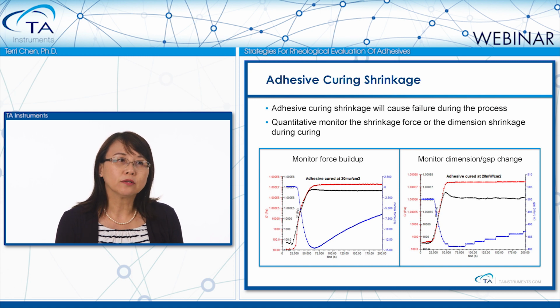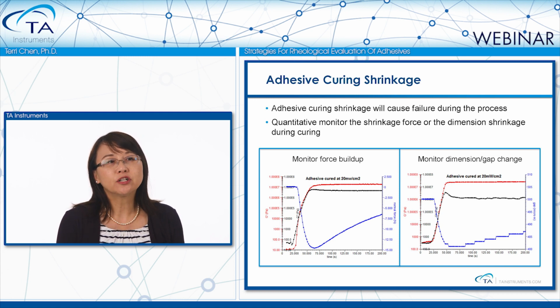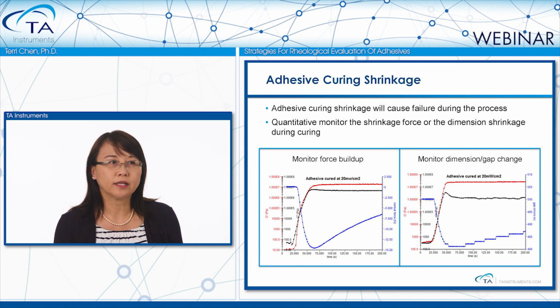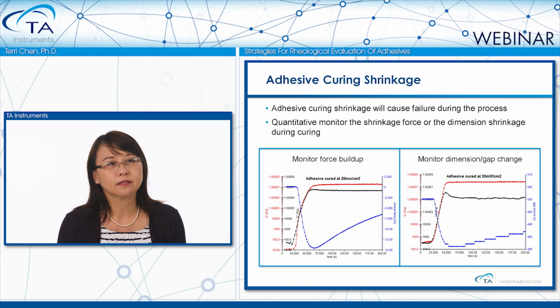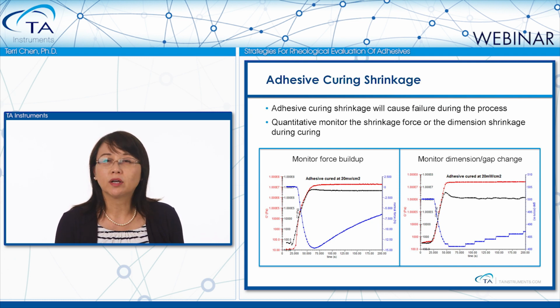In most cases, when material cures, it shrinks in dimension. Adhesive curing shrinkage can cause product failure during the process. Using a rheometer with a UV curing accessory, we can quantitatively monitor this shrinking phenomenon.